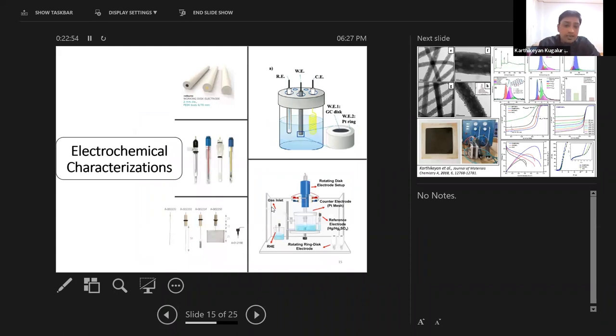And we are using the electrochemical characterization. Once we develop the material, the material will be used for the deposition of electrocatalyst. The electrocatalyst has to be characterized prior to the operation. In order to characterize with this electrochemical characterization, we are typically using the cyclic voltammetry technique and the rotating disc electrode for understanding the linear sweep voltammetry and other electrochemical characterizations. This system consists of three different electrodes: the working electrode, reference electrode, and counter electrode. And you will also have the electrolyte inside.